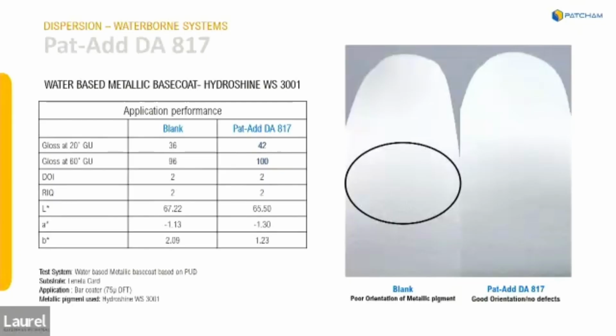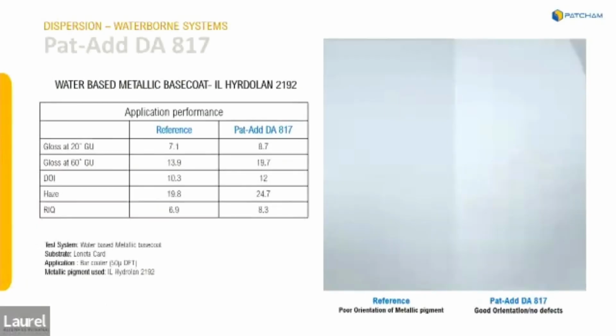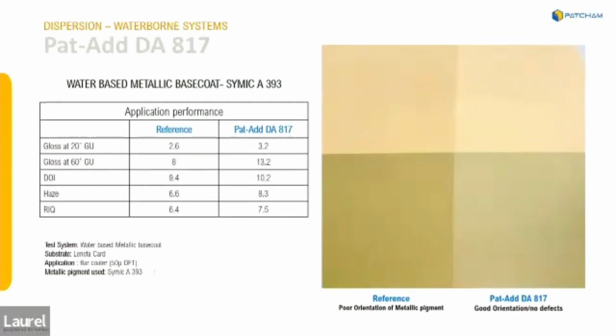It also has an impact on the orientation of flakes, as you can see here, of metallic flakes in a waterborne system. That's always been a challenge because water doesn't evaporate very quickly. It evaporates at its own desire, depending on relative humidity and so forth. And so the structuring of these dispersed particles is captured during the application process to prevent the rotation of that pigment flake because of the structuring of the dispersing additive itself. Several examples with other effect pigments. In more realistic colors with other transparent coatings, pigment dispersions.